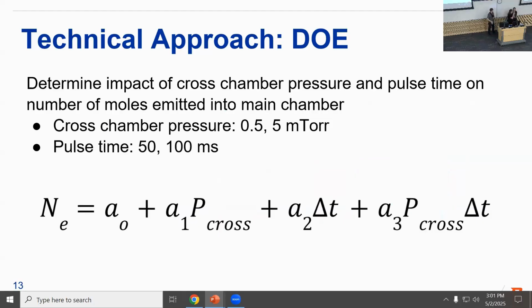Okay, as for our DOE, we decided to look at both cross-chamber pressure and pulse time, as we've discussed before, basically to determine the impact of these variables on the number of molecules emitted into the main chamber. So first off, we chose 2 cross-chamber pressures, 0.5 and 5 millitorr, to stay within the range of the RGA sensor, and also 2 pulse times of 50 and 100 milliseconds in order to test the more mid-range pulse times that we were going to look at.